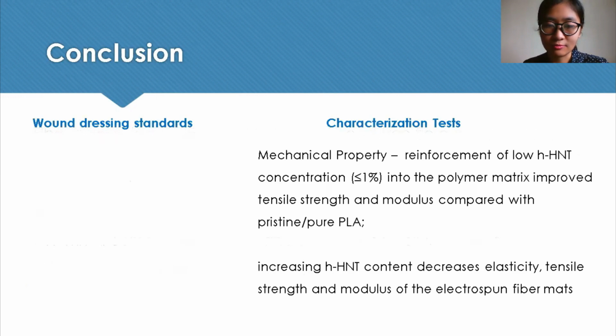Consequently, the reinforcement of low HHNT concentration, less than or equal to 1%, into the polymer matrix improved tensile strength and modulus compared with pristine or pure PLA. So we can say that the conformability is good at 1% HHNT content. However, increasing HHNT content further decreases the elasticity of the fiber mat, which may hinder the conformability of the material when applied to the wound surface subject to movement.